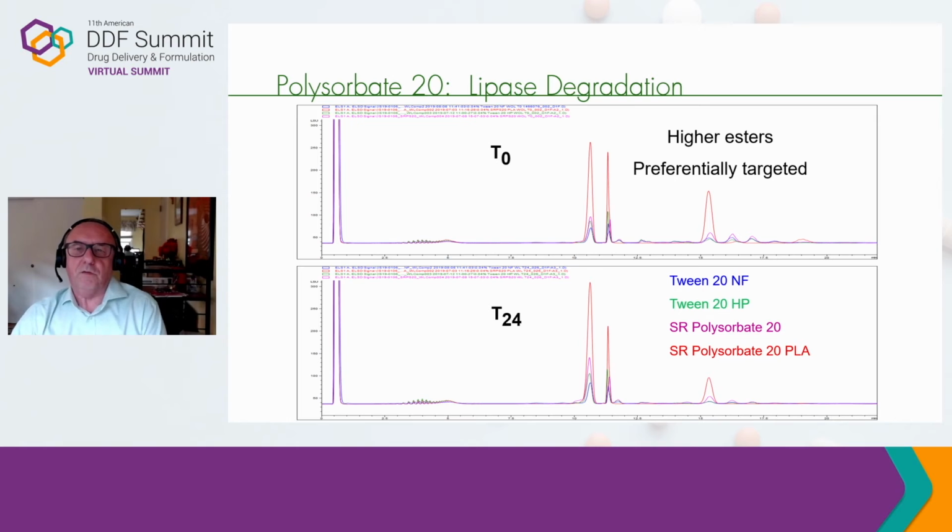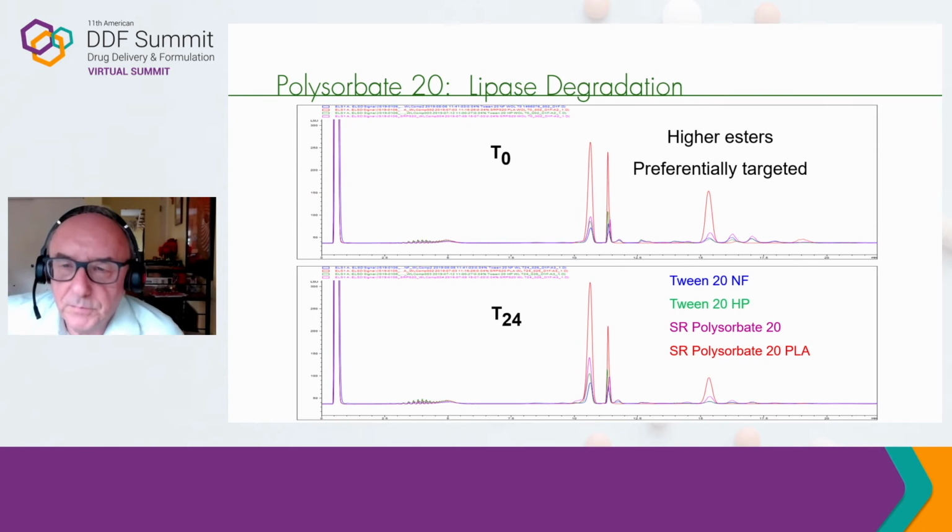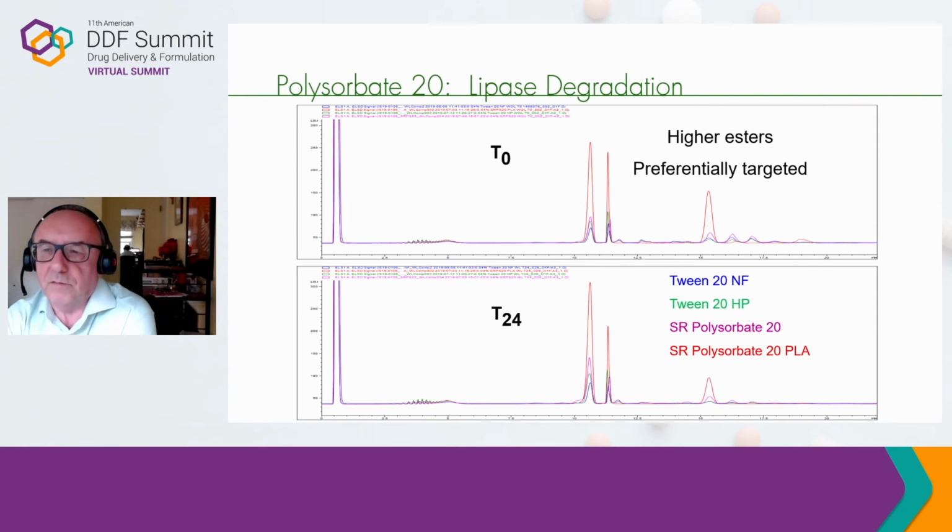So this slide shows a typical chromatogram we obtained by our reverse phase HPLC method using ELSD. And I should add that the composition of individual species has been assigned using high resolution mass spectrometry. As with other methods, we essentially separate according to the degree of esterification, starting with early eluting non-alkylated species, including free PEG, and ending with higher tetraesters.